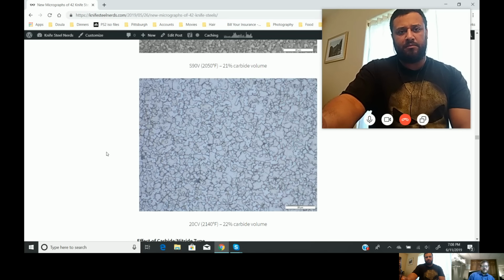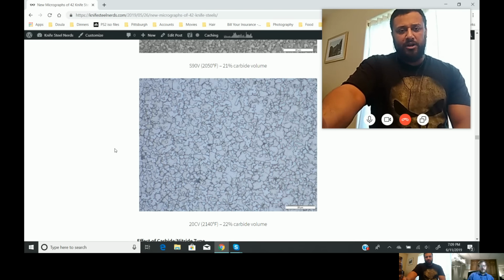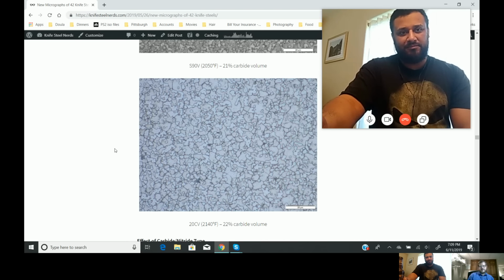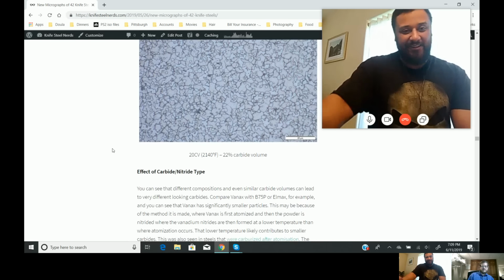And in our toughness testing, 20CV and M390 had very similar toughness, and the carbide structures also look very similar. So this is 20CV right here. It has a similar amount of carbide to S90V, but more of it is chromium carbide instead of vanadium carbide, so less wear resistance for the same amount of carbide. The amount of carbide is roughly equal to the toughness that you get. But the 20CV toughness looked pretty good. The 20CV was as tough as S35VN, even though it had more carbide. So again, differences in grain size or matrix composition or something gives it good toughness for its level of carbide. That's interesting, huh? Wow.